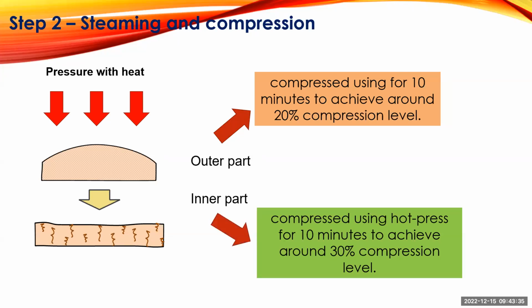The outer part and inner part will be subjected to different steaming and compression schedules. For the outer part, we will compress using 10 minutes to achieve around 20% compression level. For the inner part, it will be compressed using a hot press for 10 minutes to achieve around 30% compression level.